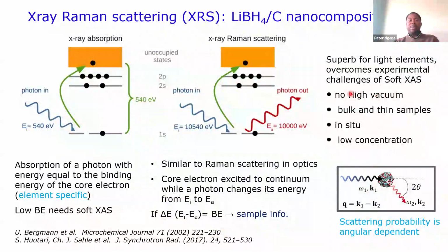Yeah. And why is this very interesting for us? Of course, all the X-ray absorption spectroscopy is element specific. In this case, because we can use high energy X-rays. If you have a light element like lithium, or want to look at boron, you need to use soft X-rays to do that, because you need to go to low energy, which will correspond to the K edge of your element. But then you need to have high vacuum. You need to have a very thin sample, and hydrides don't survive under vacuum. They just decompose completely. But with X-ray Raman scattering, there's no need for that. So we can get bulk and thin samples.